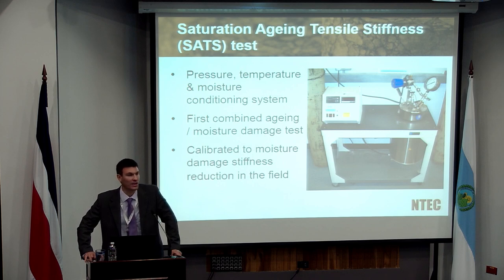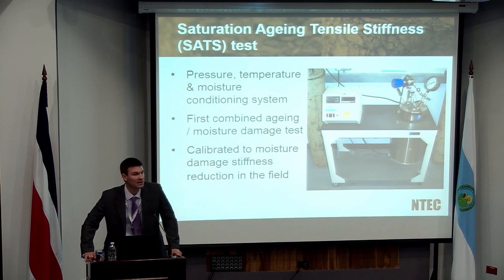So how does it work? Well, very simply, you take 5 specimens. These could be specimens that were taken from a proper road job. These could be cores taken out from the road, 100 millimeters in diameter, about 60 millimeters in height. So very much like a Marshall asphalt specimen. Or we could make them in the lab. We could use a gyratory compactor and produce specimens, usually using a 150 millimeter geometry and then coring out the internal 100 millimeters. Or we could make a slab and core out slabs to produce those 5 individual specimens.